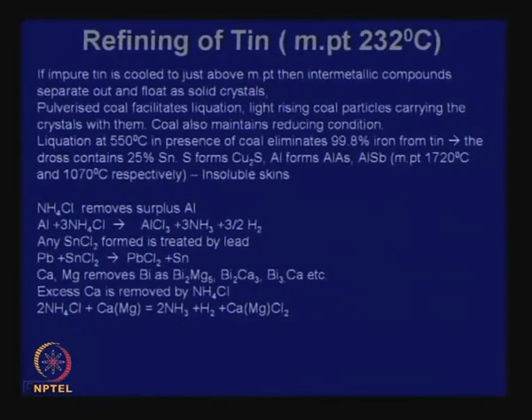So, when there is a bulk of molten impure tin, the impurities inside are not melting, so they will float up. And there are some age-old techniques to help these crystals float up. It is done by adding charcoal, because charcoal is a very light material; charcoal particles will float, and in that process they will carry those impurity intermetallic compounds to the surface also. These things evolved thousands of years ago, more than 2000 years ago. Somebody found how to do these techniques. So, you go just above the melting point, and intermetallic compounds separate out and float as crystals.